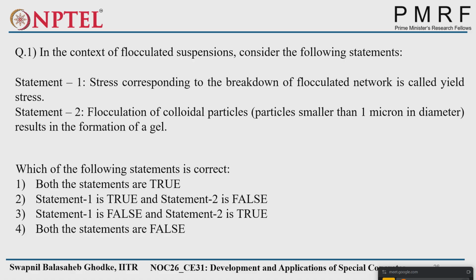Both the statements are true actually. We saw both the statements in the brief overview also, because stress corresponding to the breakdown of flocculated network: the flocculated network has internal forces but weak internal forces. That's why a smaller amount of force allows it to break down, and that smaller amount of force is called yield stress. And the second statement is flocculation of colloidal particles, that is particles smaller than 1 micron in diameter, results in the formation of gel. That is a recommended statement from the code itself.